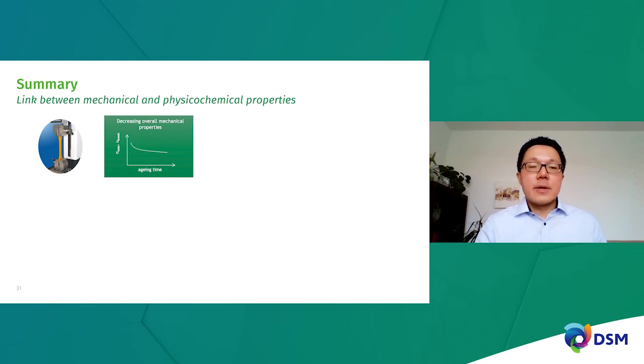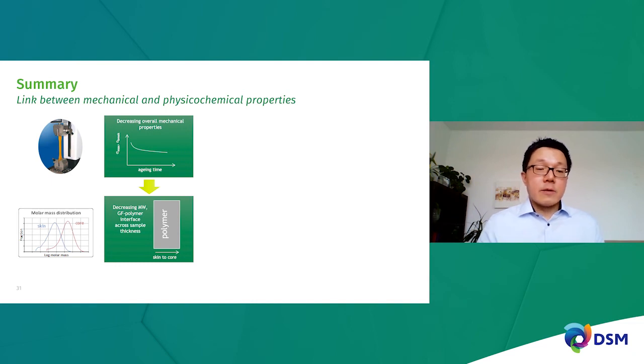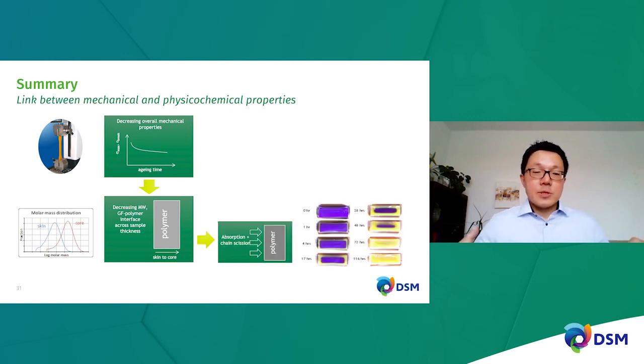To recap, just to summarize what we have been discussing so far regarding the degradation mechanisms. Typically there is a direct link between mechanical to chemical structure of polymers after aging. So when we are talking about aging of polymer in chemicals, what we start to see is usually a reduction in certain mechanical performance after aging, which is due to the decreasing of molecular weight. And if you have glass fiber in the compound, also a decrease of the interface between the glass fiber and the polymer. And this is due to the absorption of the chemicals as well as the reaction of the chemicals to the polymer, or reaction between the chemicals towards the interfacial region of the glass fiber matrix interface,